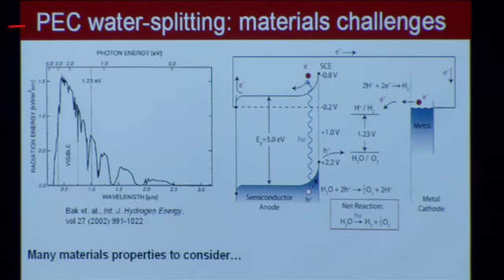So now that we know that the sun provides us with enough energy, let's take a look at the redox potentials for hydrogen and oxygen. Okay, this is where the 1.23 volts comes from. Now, I want you to also bear in mind that this hydrogen evolution potential is very similar to the redox potentials for CO2 reduction. Okay, so you could almost instantly swap out, instead of this line being hydrogen evolution, it could be CO2 to methanol, it could be CO2 to ethylene, it could be CO2 to diesel. Okay, it could be CO2 to just about anything, and it's going to be more or less at the same spot.